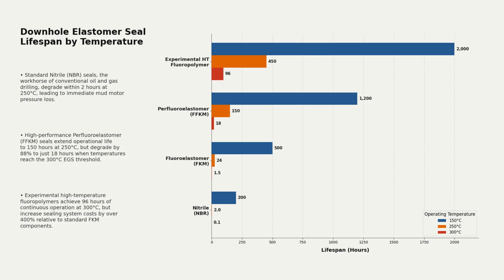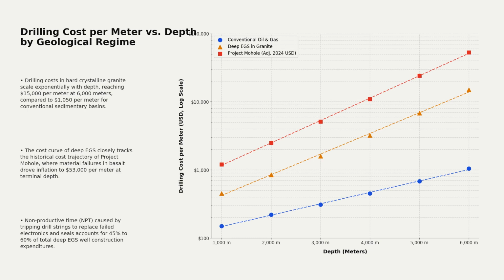High-performance perfluoroelastomer seals extend operations to 150 hours at 250 degrees, but their lifespan drops by 88% at 300 degrees. Experimental fluoropolymers can withstand 96 hours at 300 degrees, but increase sealing system costs by over 400%. These material limitations dictate the exponential cost curves of deep crustal drilling. Drilling through hard crystalline granite to 6,000 meters costs $15,000 per meter, compared to just $1,050 in conventional sedimentary basins.